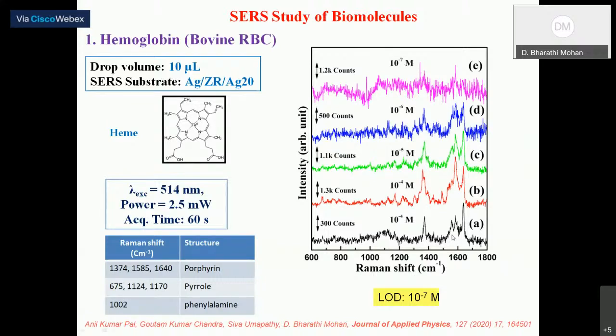And as you can see that the Raman modes of the hemoglobin decrease with decreasing the concentration. So the limit of detection of the hemoglobin on silver-based substrate is found to be 10 power minus 7 molarity.